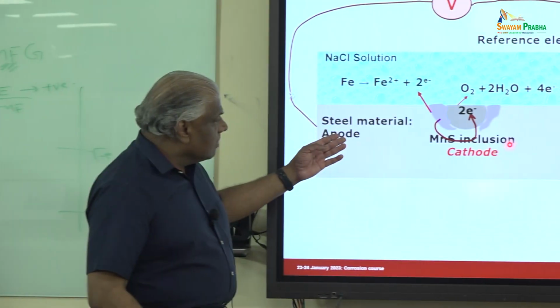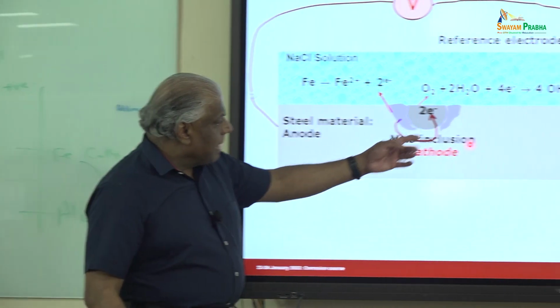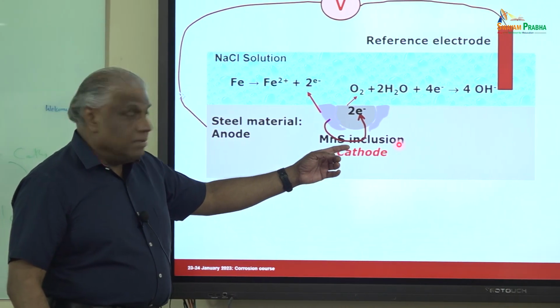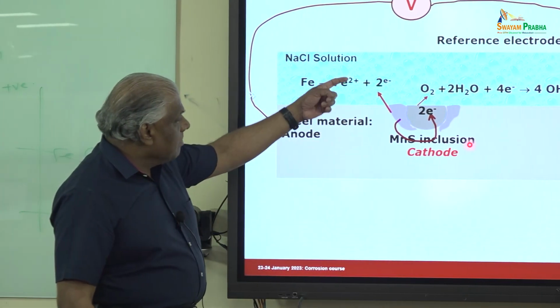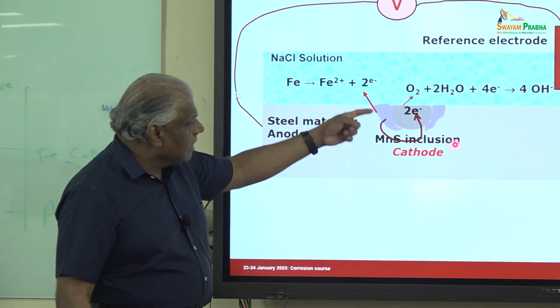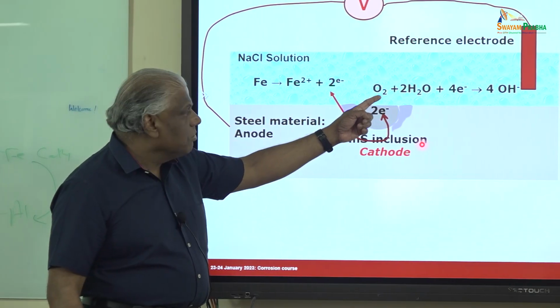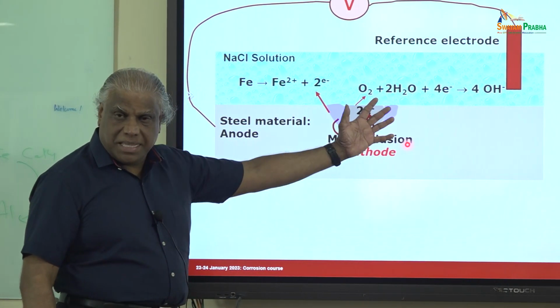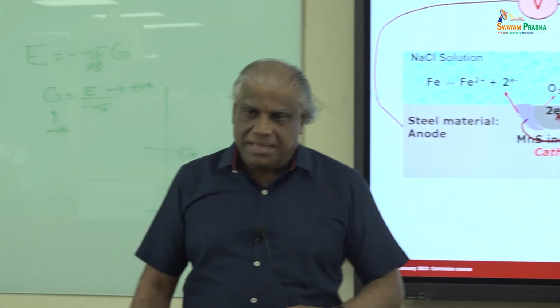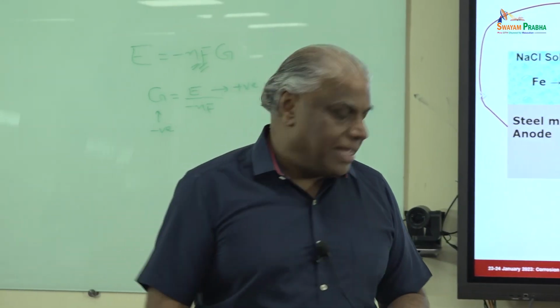So in a stainless steel substrate, you have the manganese sulfide inclusions. The iron part will dissolve as iron 2 plus, but that electron will be used in the manganese sulfide inclusions for the cathode reaction. So you can see that on the same surface, both reactions are taking place and the corrosion is occurring, like that.